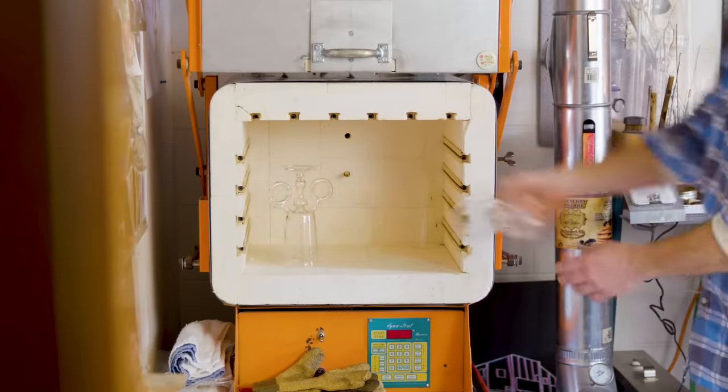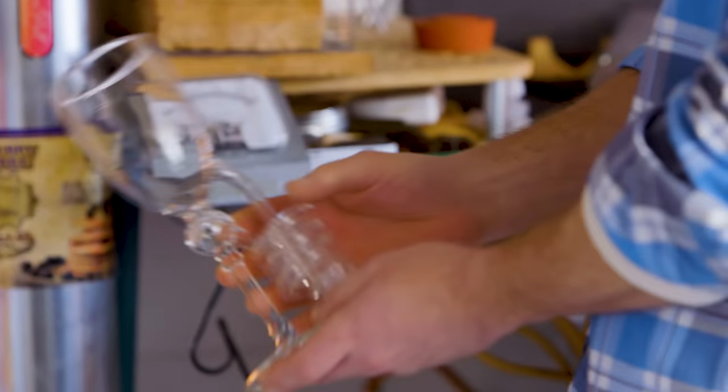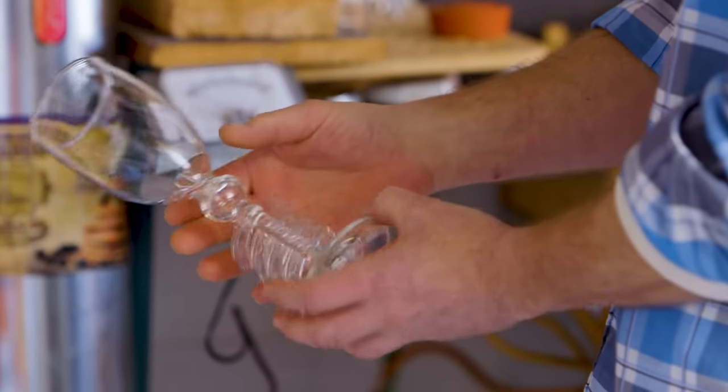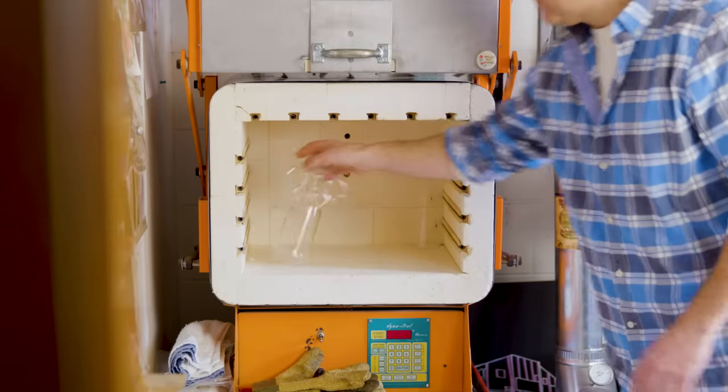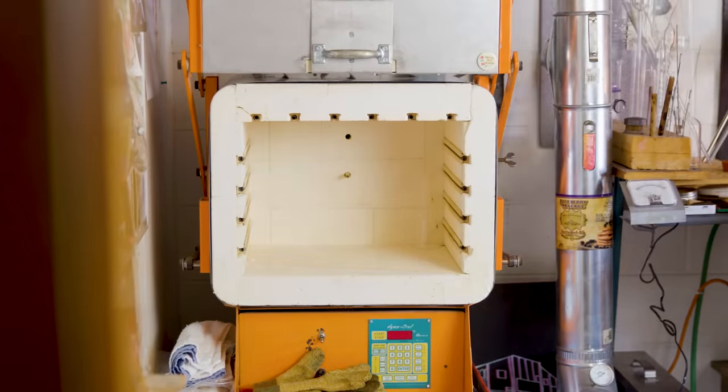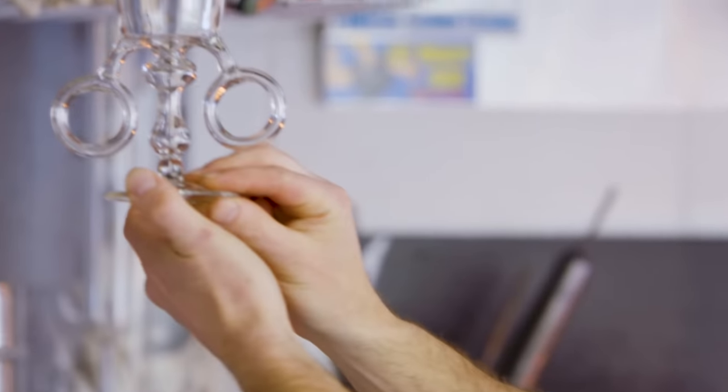Depending on your oven, if you have a brick oven, it will hold the heat longer. If you have a Fiberfrax oven, it will cool a lot faster. I have one that's fire brick, so it holds the heat longer. And it's more of a ramp down cooling versus a shelf drop off cooling.